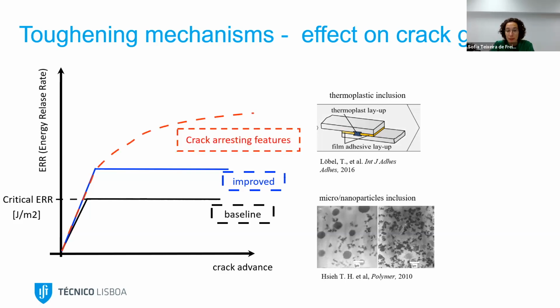But we can also add crack arresting features, which means that once the crack advances, the energy necessary for the crack to open increases every time the crack advances. While in the blue line, we see that once it reaches the critical energy, the energy is always the same, meaning that whatever crack advances, the energy necessary to open the crack is always the same. However, in the red line, every crack advance, you need more energy to open the crack. So this is the ideal solution, because every time the crack is advancing, we are arresting the crack.